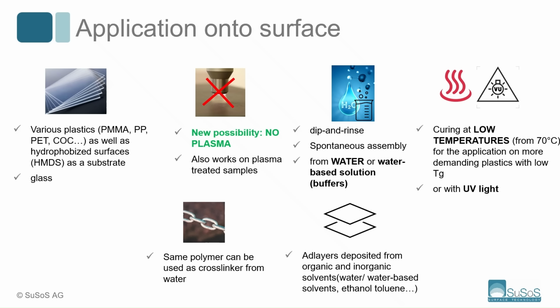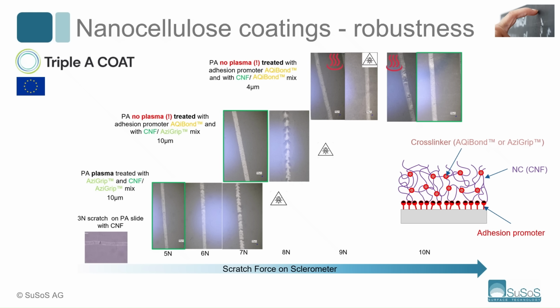The same polymer can be used here as a cross-linker, also from water application, and the added layer, for example the nanocellulose, can be deposited from both organic and inorganic solvents, so water, toluene, ethanol, etc. And here I would like to show an example of how we could increase the robustness of the nanocellulose coating for the AAA project. So we have a plastic slide, a plastic surface, and we try to deposit on top the CNF, the fiber nanocellulose. And as you can see, if we don't use anything, just the substrate with the nanocellulose, we have a scratch force of approximately 3 Newton, which is very low.